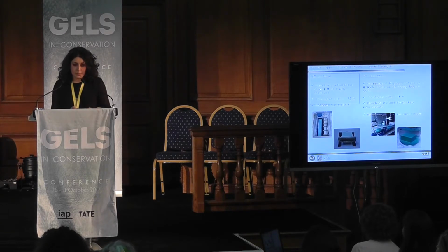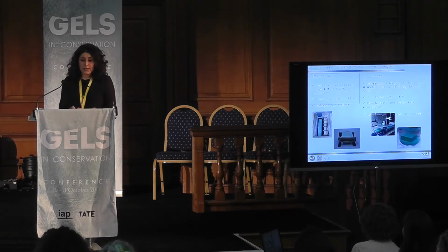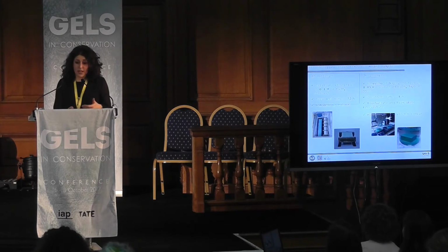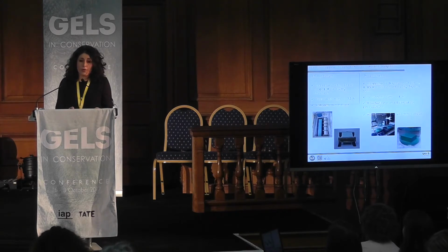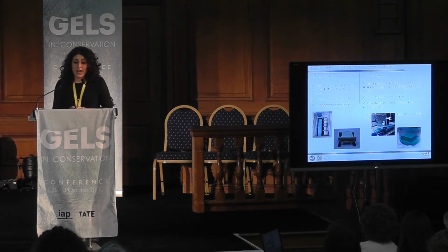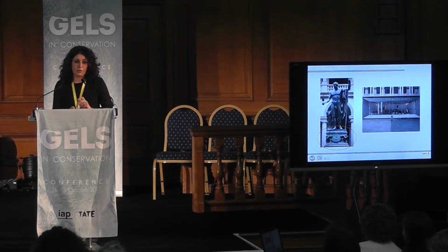Which are the differences? Firstly, the color, more intense in the second attempt and quite faint in the other one. But secondly, the composition of the stains that we have synthesized. In the first case, X-ray diffraction detected the presence of posnjakite. In the second attempt, posnjakite and brochantite. Notwithstanding these results, we used the first attempt because we are focused on this kind of real case.